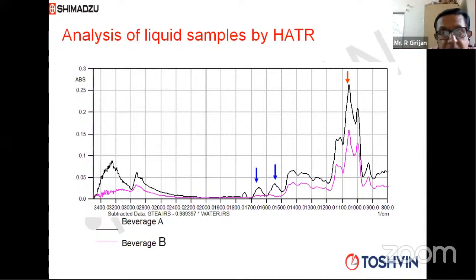But if I record the spectrum of these two beverages using an HATR in FTIR, my IR spectra are going to be totally different. I can differentiate between beverage A and beverage B. There is a clear-cut difference and extra peaks are coming. So samples can be differentiated by recording the IR spectrum, and this is performed with the help of a HATR.